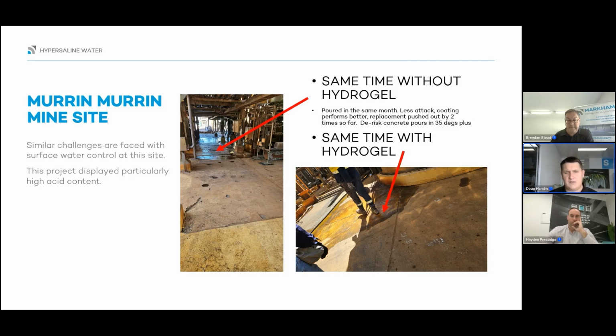So again, this site had aggressive chemicals, acids, that type of thing. The washdown water, I'm not sure on the salinity of this, but I'm imagining it's high and also has other chemicals by its nature, and that's getting washed down regularly. It's having to deal with leakages, spills, that type of thing. So very harsh environments, and a real true testament to this: if you get that concrete sealed up and that porosity blocked, you go a long way to getting the best service life out of the concrete.